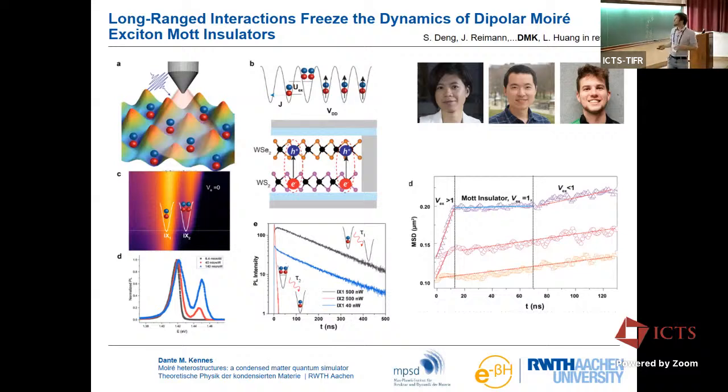Yeah? So what Levi at Purdue did is they looked at such a sample. They excited with just a laser a bunch of excitons. And if you have few excitons, what you see is this yellow line here. Yeah? And they can time resolve how the exciton cloud that they create spreads over time, and it just shows diffusive behavior. That's what you would expect. Yeah? So it just kind of diffuses out the exciton cloud that you have made.